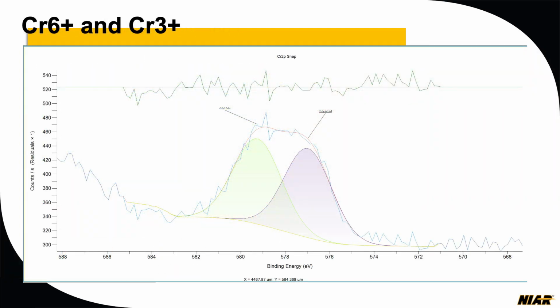So for the chrome, we identified there is Cr6 and there is Cr3. Initially, we did a lot of initial test parameters, and Cr6 is so reactive, it's even reacting with the flood gun electrons that we are putting on the surface. So we were always constantly getting Cr3. Luckily, we had a software update just a few days back, and that helped to analyze the sample, and we were able to detect Cr6 now. So that's your Cr6, and that's your Cr3.